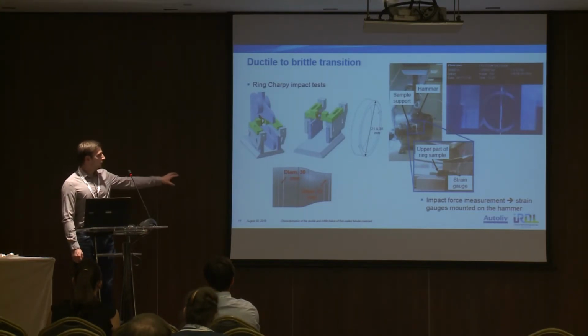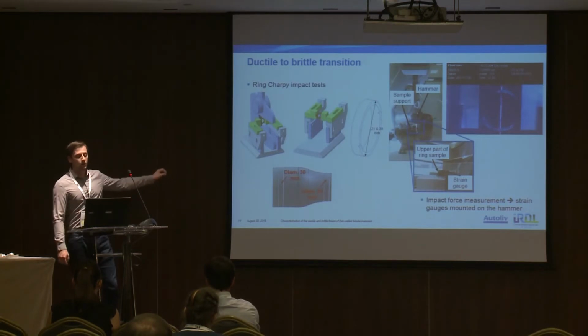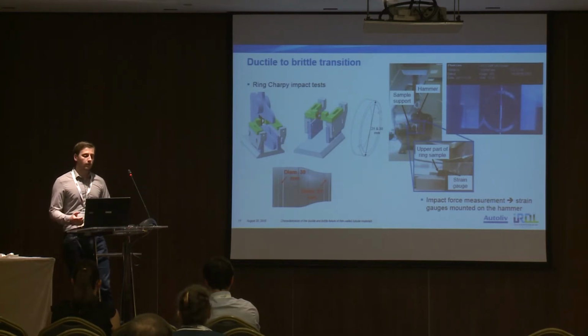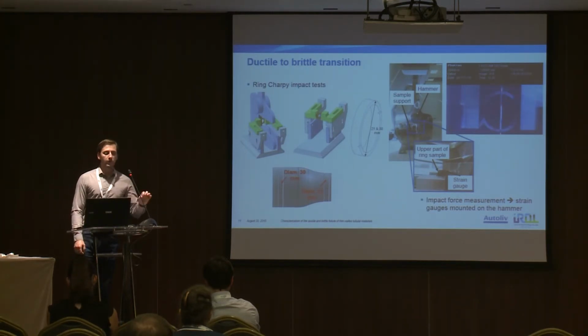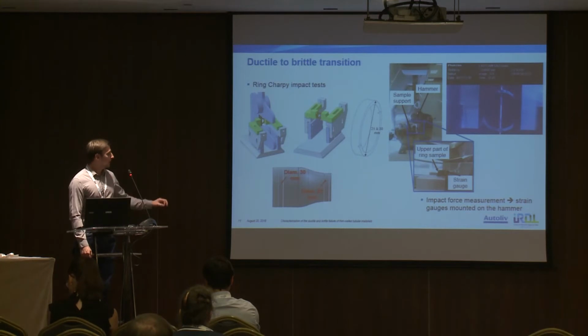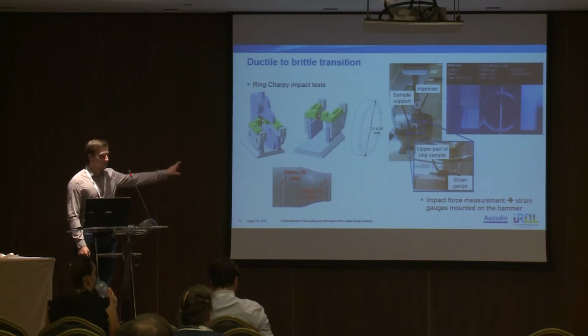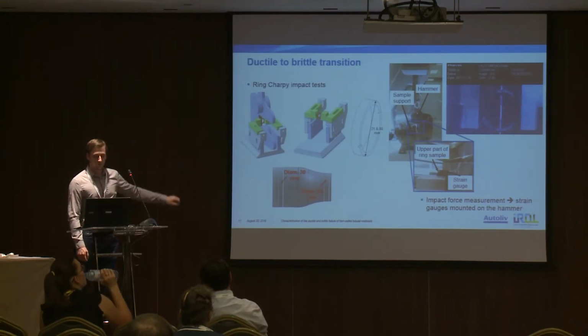Also, there are 2 diameters tested: a 30 millimeter diameter, which corresponds to the material at the initial state, and a second diameter of 21 millimeters, which corresponds to a critical part of the structure. And for our industrial company, it will be very interesting to focus on these 2 samples.